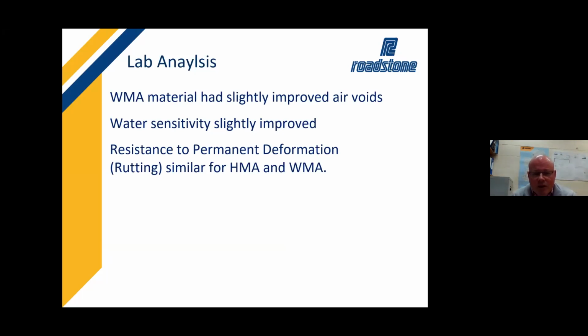And then we've also seen a similar performance for resistance to permanent deformation. That's an interesting thing to see, because again, the aging process that normally would happen with the standard hot mix asphalt would result in maybe a stiffer mix, and that stiffer mix would usually result in slightly better permanent deformation. But on this occasion, we found that the two of them performed very similarly, so no big difference between them.